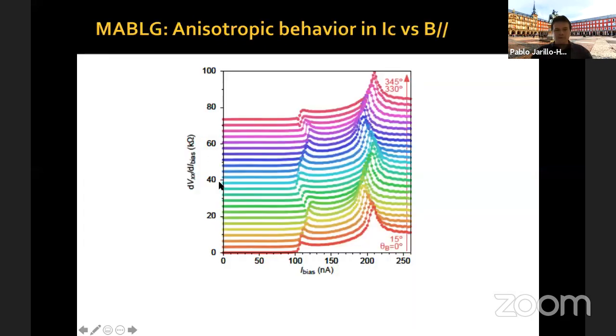This can be perhaps a bit more clearly seen in these differential resistance curves as a function of current bias. You can see these different curves, which are offset. The offset is just magnetic field rotation increments of 15 degrees. The red trace is 0 degrees orientation, and you have a finite switching current. Now you can see that the switching current evolves with the magnetic field. It has two maxima, indicating this twofold anisotropy. So now we have this nematicity in the superconducting state of the system.